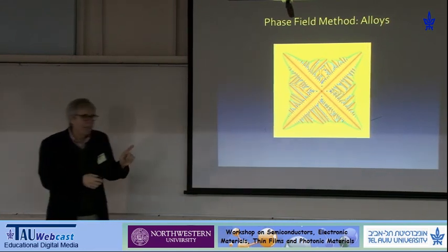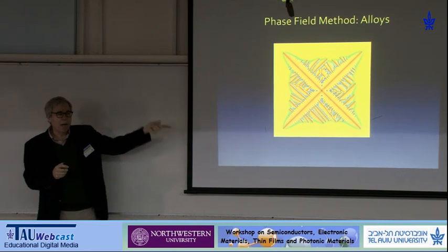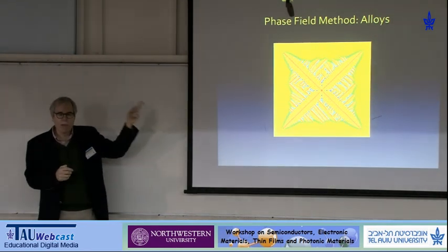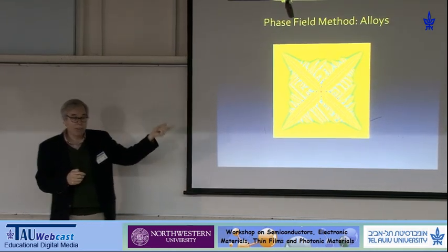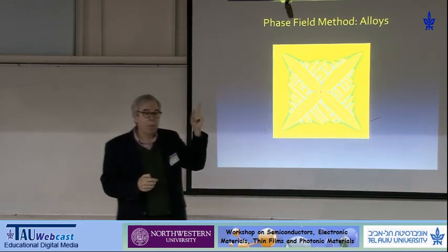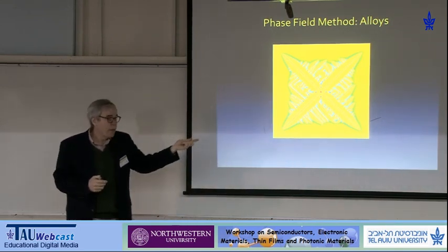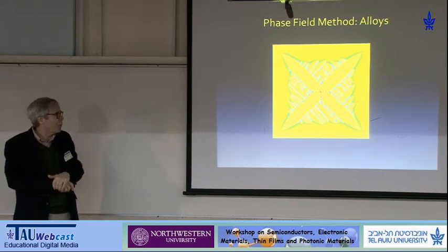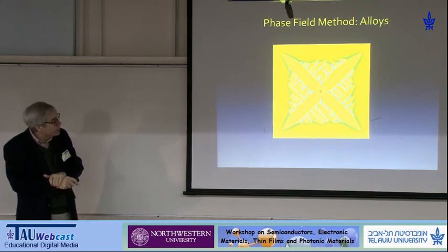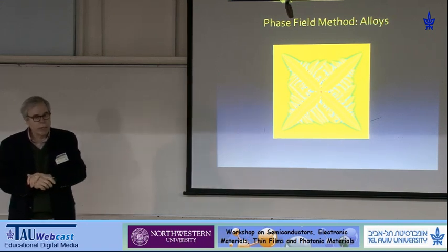Okay. So now think about the pipe, right? This calculation is not quantitatively correct. It looks like a dendrite, kind of smells like a dendrite, but it is not a dendrite. And in fact, Bill Boettinger and Jim Warren would admit this. It is not quantitatively correct. The amount of solute segregation that you get here is not correct, but it looks a lot like a dendrite.